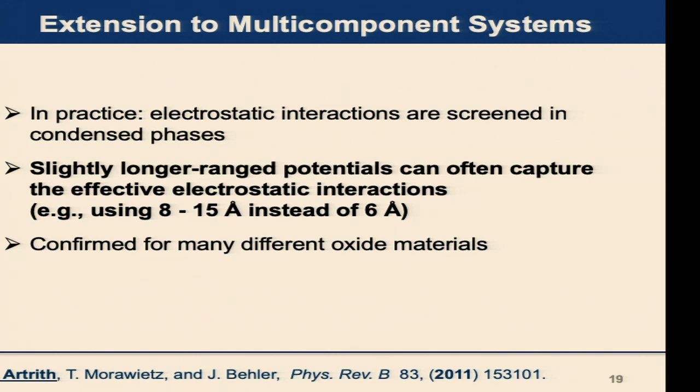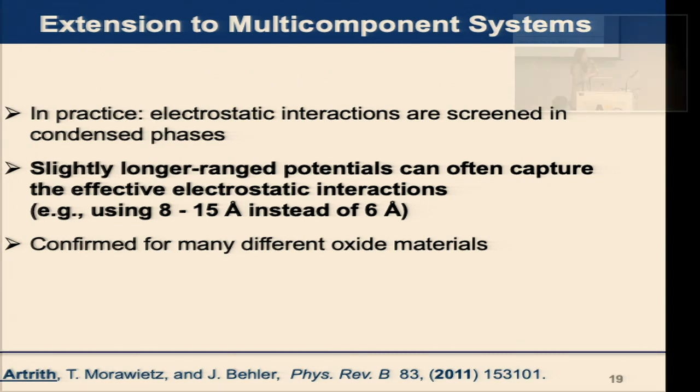if we use the same diagram as Behler-Parrinello proposed in 2007, but increase the cutoff radius larger, for example, usually we use 6 angstrom, but we could use 8 to 15 instead of the short range, this can also already capture the long-range interaction. But there are many atoms in the radial cutoff. We already tested with many molecules and many different systems.